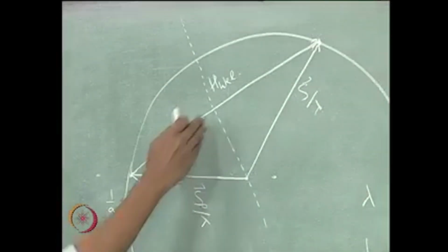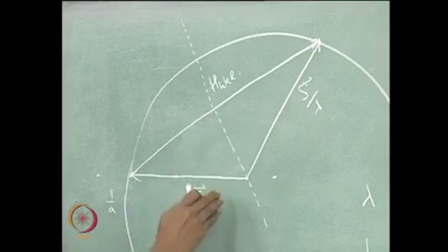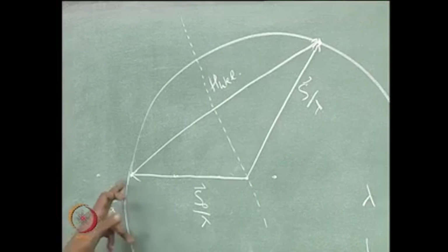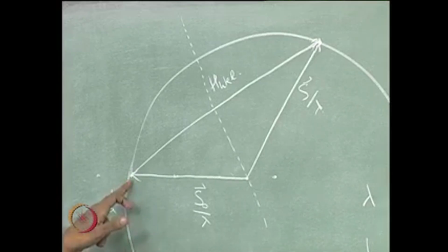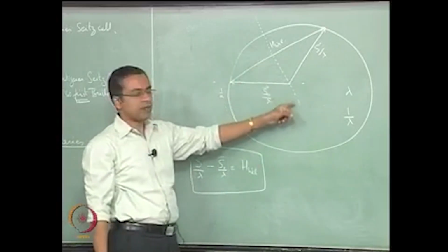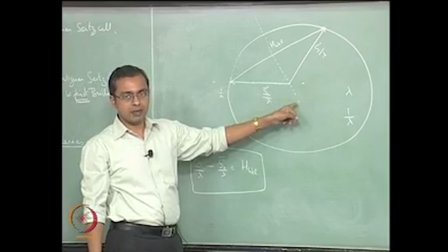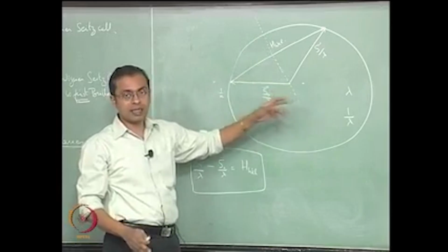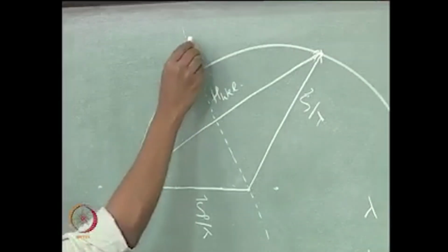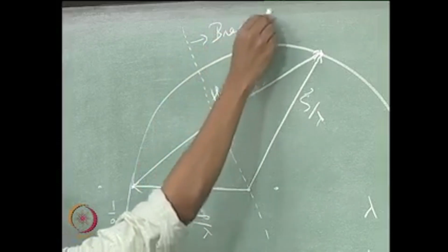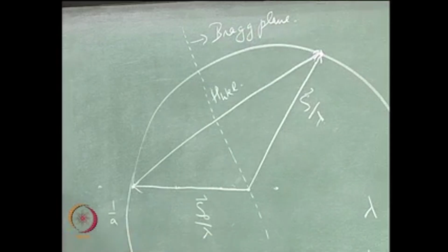So what have we got here? This perpendicular bisector here is actually the perpendicular bisector of a valid reciprocal lattice vector. The origin is this, so the origin is fixed, this is some valid reciprocal lattice vector HKL, I have just drawn the perpendicular bisector to that valid reciprocal lattice vector, right, and therefore by our definition this perpendicular bisector is a Bragg plane, alright. So this is a Bragg plane. In 2 dimensions it is showing up as a line, but it is a plane. If you look at a sphere, it is a plane, right.